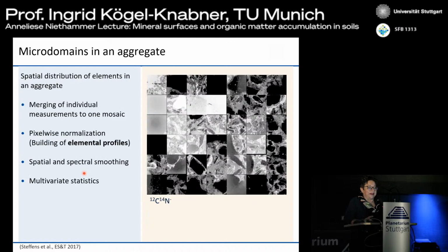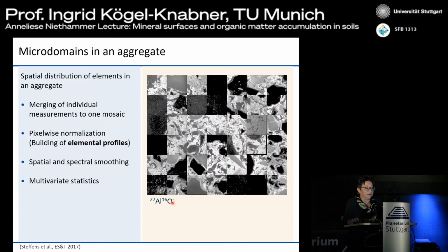And we then looked at these distributions of nitrogen, of Si, for example, of aluminum, and there was a lot of spectral smoothing and normalization of these data and a lot of multivariate statistics. And this is what we did with Derek Rogge from DLR. And we used an approach that is normally used in remote sensing and applied it to look at our aggregate.